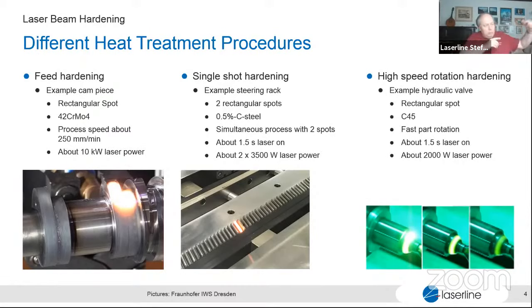Let me speak backwards a little bit about the principles of laser beam hardening. The classical process is feed hardening. That means we have a certain spot moving over the part, or the part moving under the spot. The second, which I already mentioned, is single shot hardening: a spot applied to the part, on, off, done. And the third version is rotating a part very fast, applying a spot, generating a hot ring by this fast rotation of the part. With this hot ring, we make a local hardening of a ring, or even of a cylindrical shape. These are the three main principles of laser beam hardening processing.